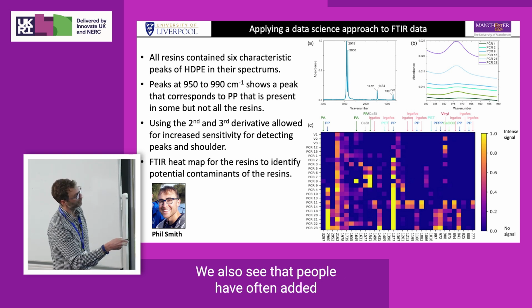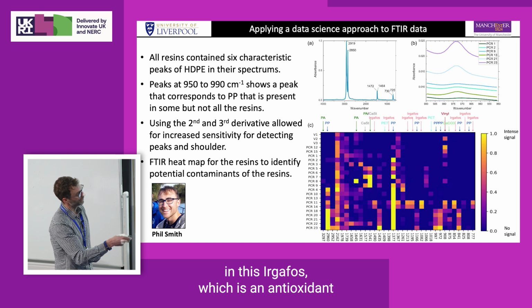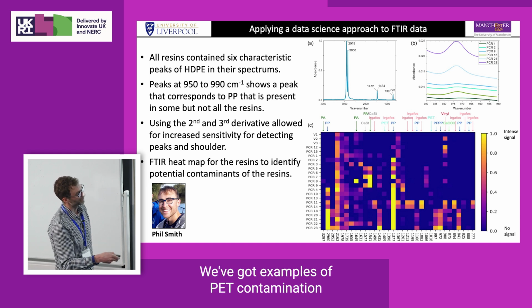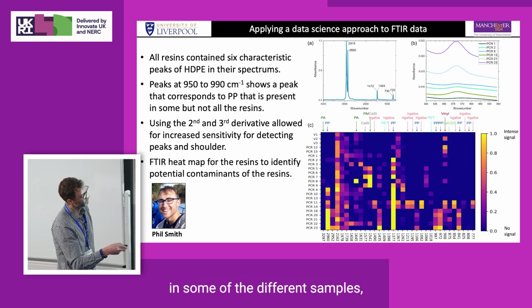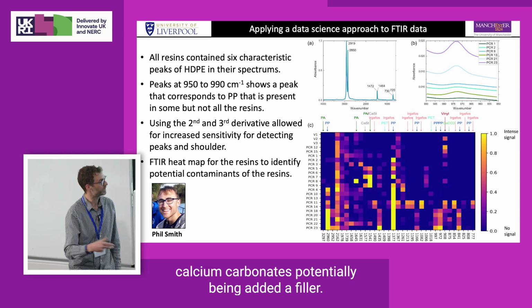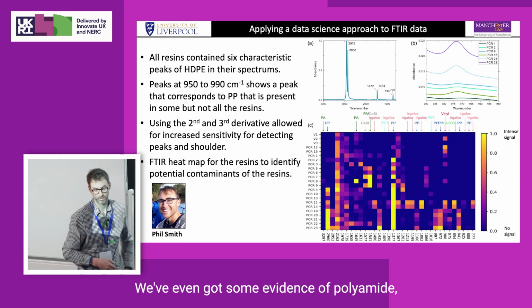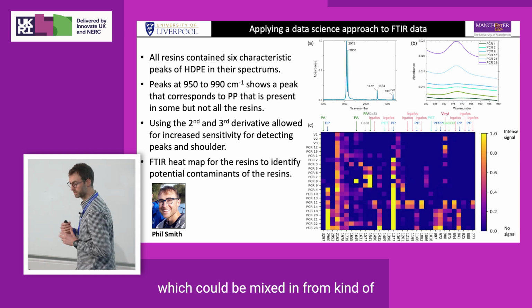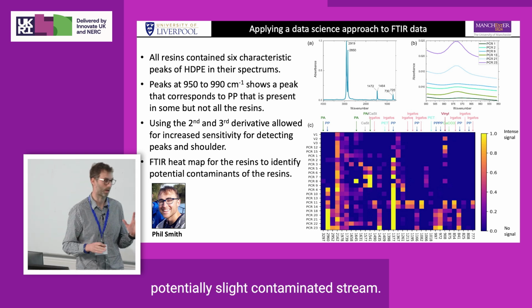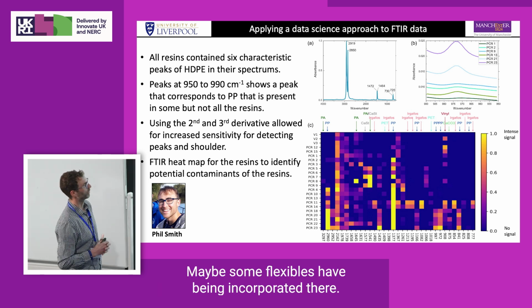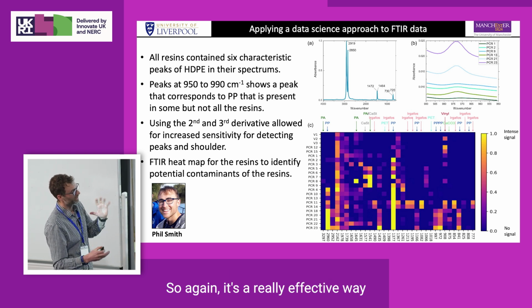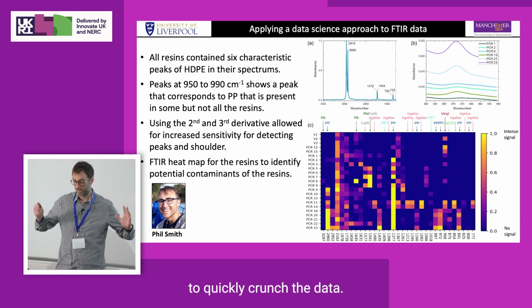We also see that people have often added Irganox, which is an antioxidant. We've got examples of PET contamination in some of the different samples. Calcium carbonate's potentially been added as a filler. We've even got some evidence of polyamide, which could be mixed in from a potentially slightly contaminated stream. Maybe some flexibles have been incorporated there. So again, it's a really effective way to quickly crunch the data.